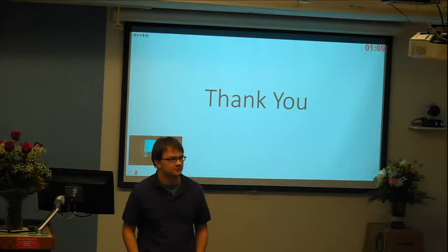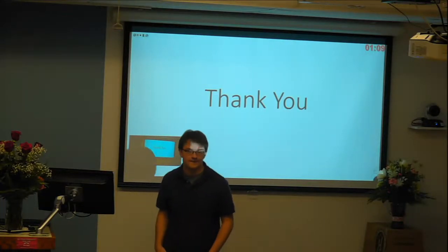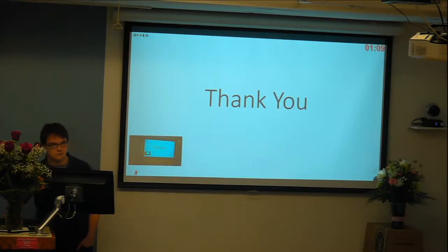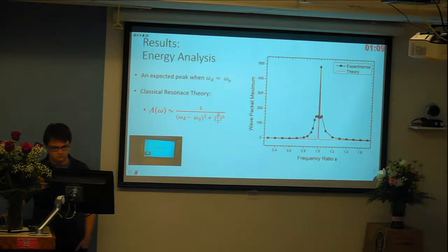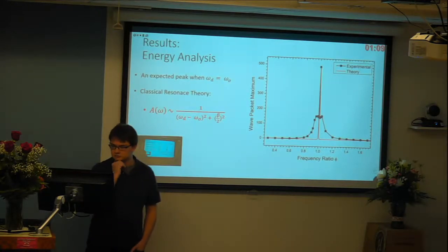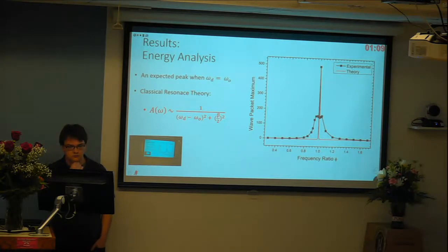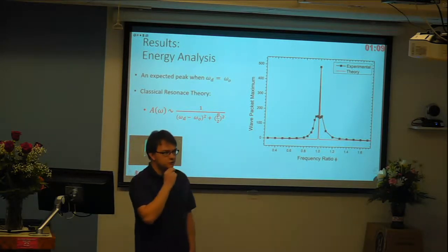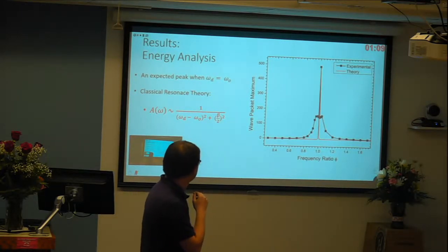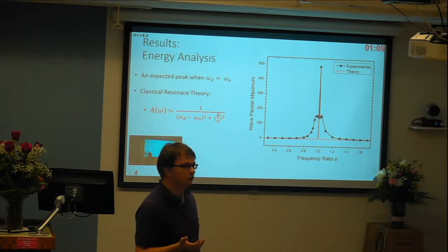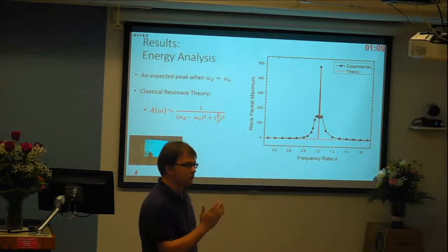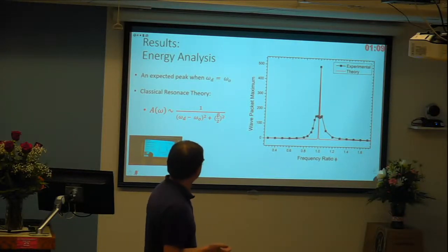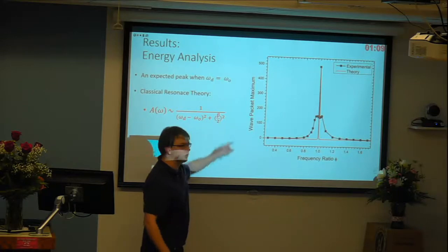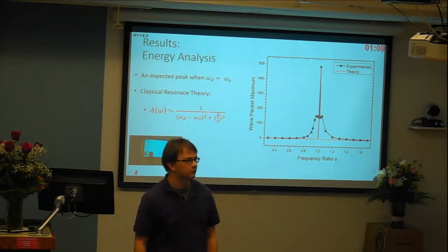Diane? On the previous slide with the results, there is this extra broadening of the experimental curve that's not there, right? Well, when I plotted the theoretical curve, I didn't do any calculations for the broadening of the peak. I just wanted to show that the peak will line up with classical treatment. So the broadening term is here in this beta, which is related to the driving.